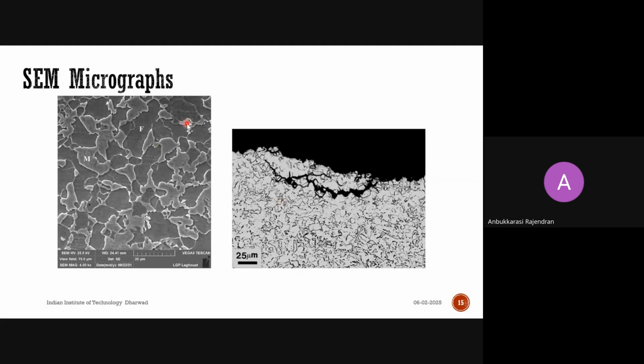In addition, SEM micrographs can be used to reveal any cracks or defects that are present. Again, this analysis requires the standard sample preparation procedure I mentioned for optical. The same thing we have to follow. And these are all after etching, in the etched condition. To reveal the features, we are supposed to do the etching.